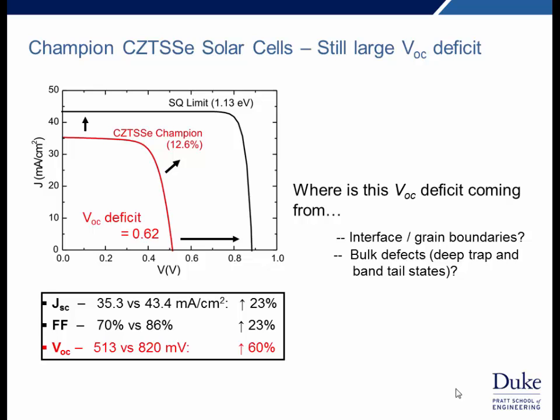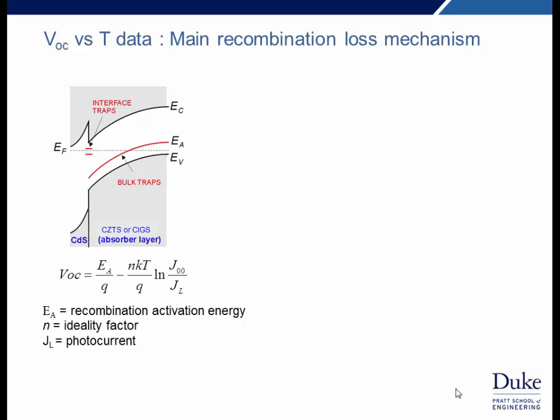Interfaces, grain boundaries, bulk defects. And so the first place that one often looks to try and address this is to look at the temperature dependence of the open circuit voltage. If we look at the expression for open circuit voltage, there are two terms. The first is the activation energy of the dominant recombination process, and the second is a temperature-dependent logarithmic term. And so if we examine VOC as a function of temperature and extrapolate to zero temperature, we can get out this activation energy for the dominant recombination process. And so in essence, this is a window into the recombination going on in the device.